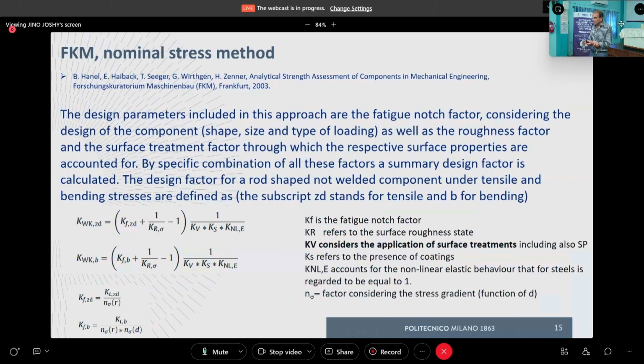KNLE considers not linear elastic behavior of the material, and if the behavior is linear, this is equal to 1, of course. And sigma is a factor that is related to the stress gradient, similar to the relative stress gradient factor that we have considered in the previous approach. So this is the way shot peening is included in the fatigue design for the FKM nominal stress approach.